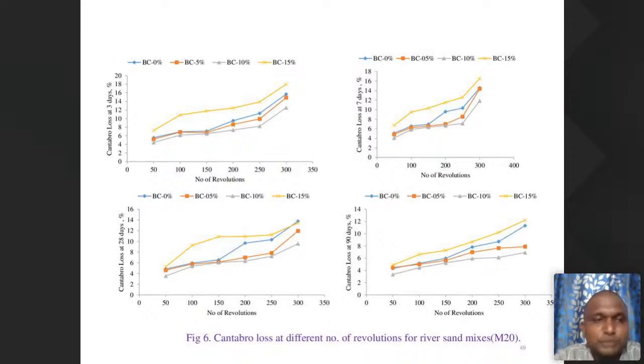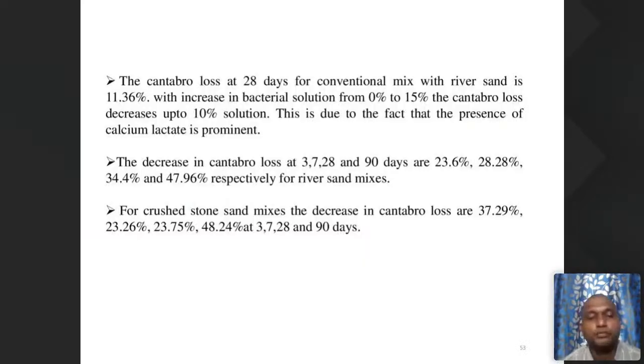If you observe, the number of revolutions is most important. We performed it for 3 days, 7 days, 28 days, and also 90 days. Only up to 90 days I have done. Here also, as the number of revolutions increases, the Cantabro loss also increases. Same like that, I performed both grades, M20 grade concrete and M40 grade concrete. Here, the number of revolutions for river sand mixes, same like that.